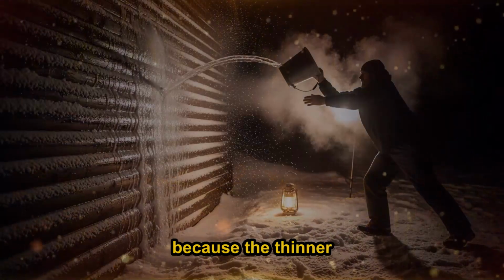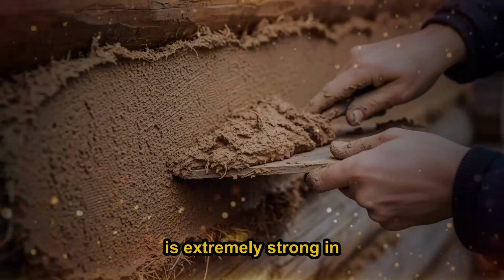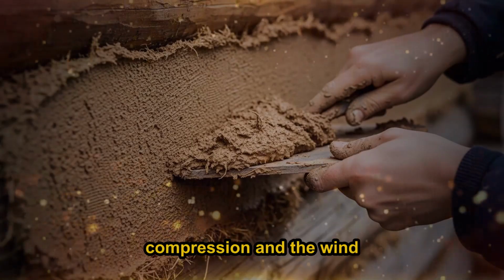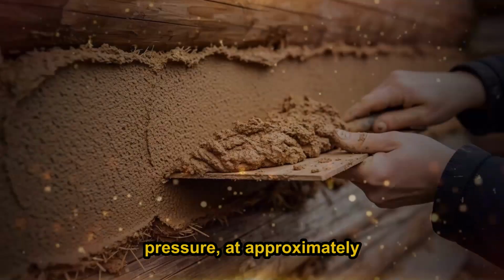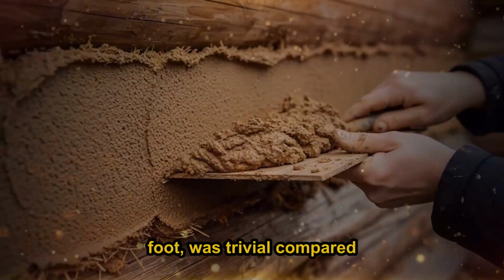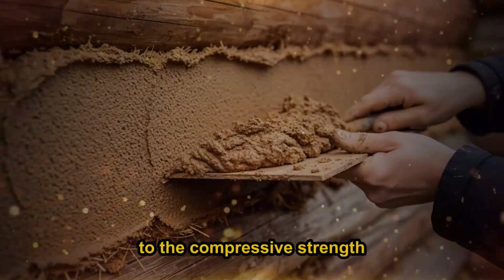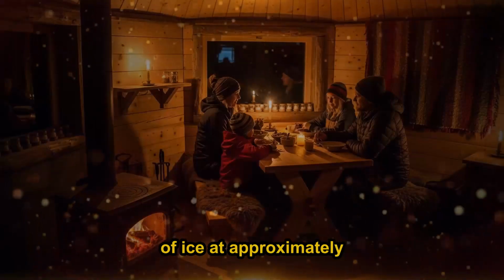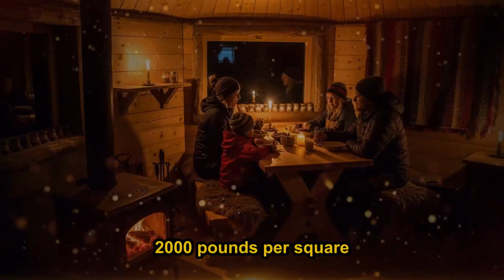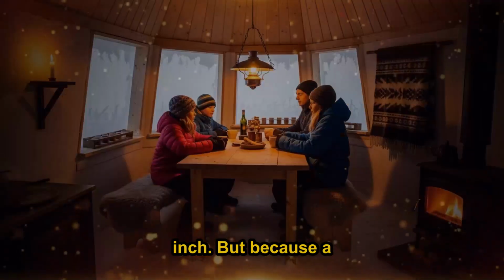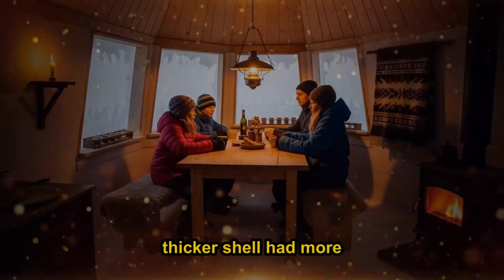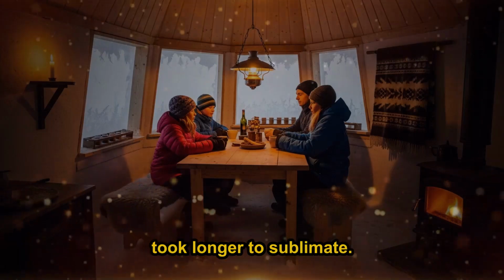Not because the thinner shell would break. Ice is extremely strong in compression, and the wind pressure, at approximately 8 pounds per square foot, was trivial compared to the compressive strength of ice at approximately 2,000 pounds per square inch. But because a thicker shell had more thermal mass and took longer to sublimate.